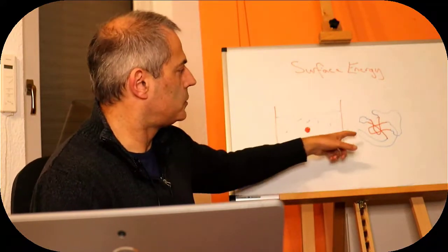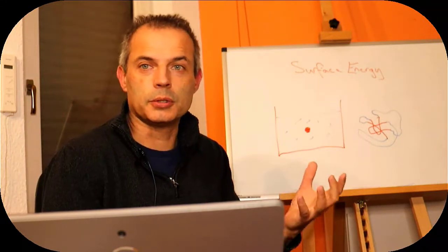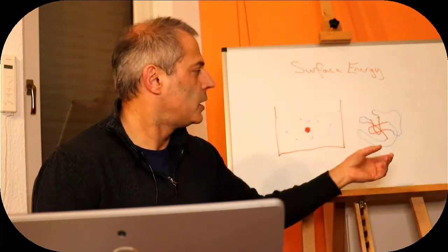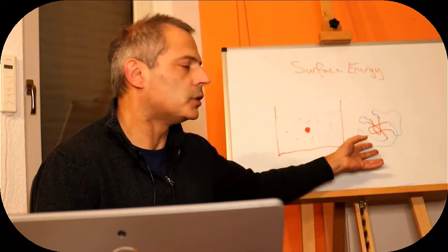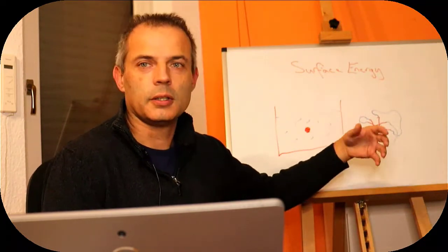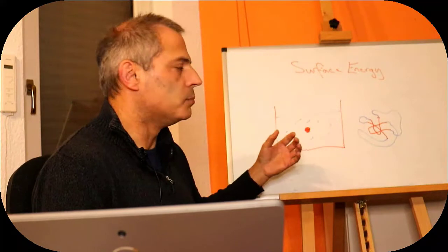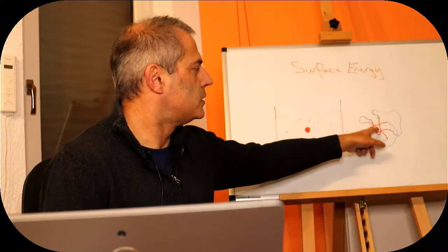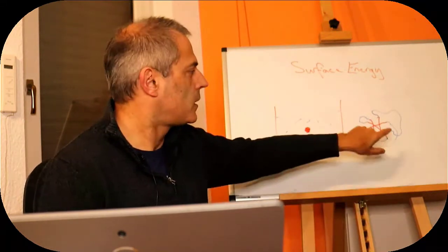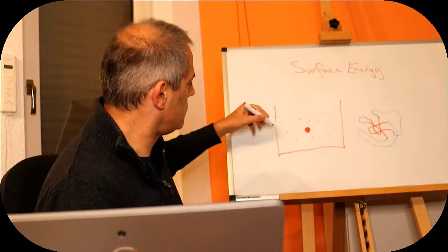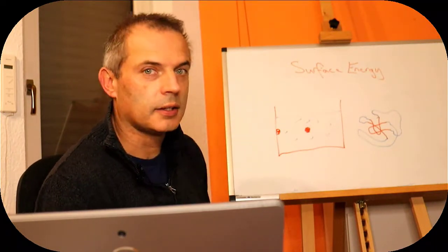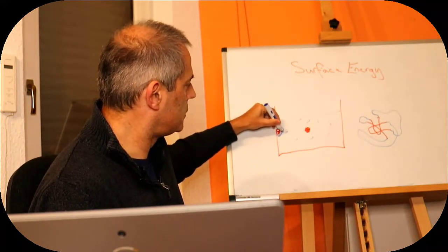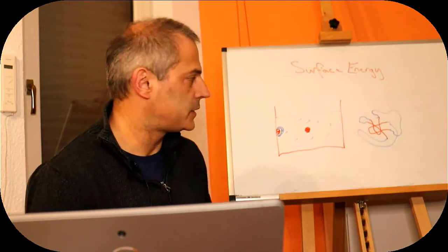If we take this protein and we move it up to a surface of glass, the hydrophilic groups, which are higher energy, will tend to bond to it, and they will tend to bond to it specifically so that it will usually be nitrogen groups on the outside that attach to the glass. If we bring it up to a hydrophobic surface, it is possible, and very likely, that the inside of it can turn inside out. So this side can go through, so let's draw it on there, and the hydrophilic part goes into the water, this little hat, or it spreads out completely flat.